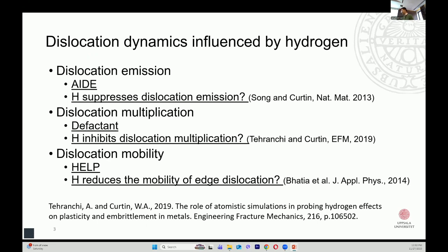In the literature, there have been several theories about the interaction between hydrogen and dislocation. There are opinions that hydrogen would promote dislocation emission, multiplication, and mobility. But there is also sufficient evidence, mainly on the opposite side, claiming the opposite. But anyway, I think a general consensus in the community is hydrogen embrittlement is really complex, and we may need more than one theory to explain the phenomena, and this is dependent on material and loading conditions.